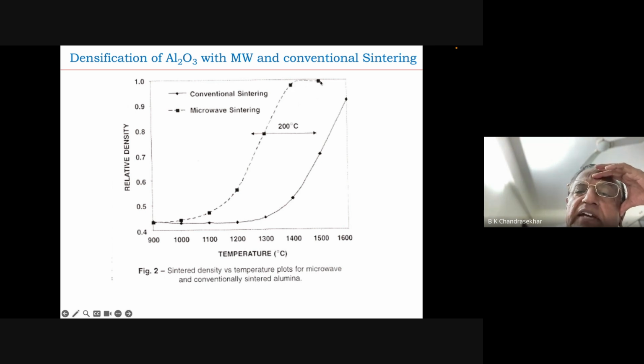This is where the soaking takes place, at the top. Typically 1 to 2 hours is the soaking period. Then you get about 99 or 99.5% theoretical density, the balance being pores, either open pores or closed pores.